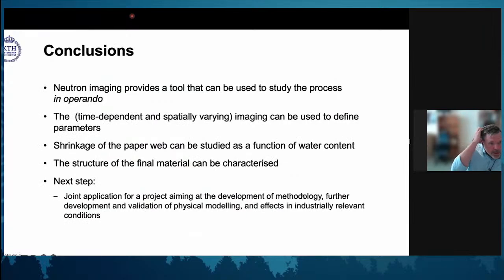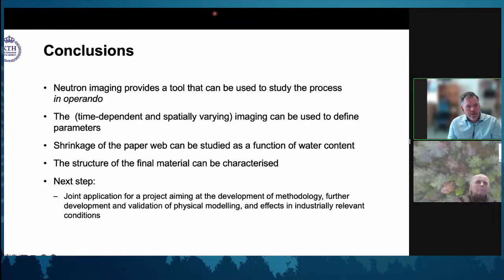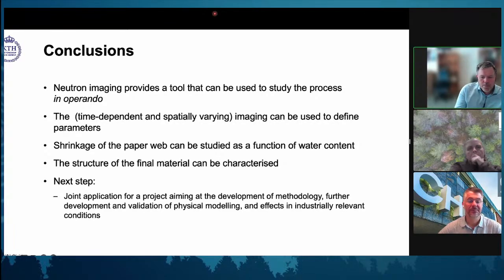So the conclusion from this study was that neutron imaging was an interesting technique. It was in operando. The time dependence and spatially varying means that we have a lot of data that helps us in extracting parameters. A little bit cool that you can look at shrinkage of paper webs. We can even look at structure of the final material, and we are together now looking at a continued project to take this further with also the dynamic system of pressing, as I said. So that is 3 things that we have done with neutrons. It can be used for fibers. It's super good if you want to separate behavior of water or not.